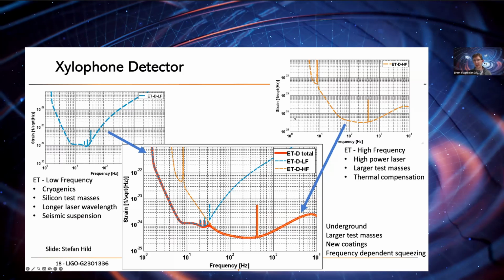Then at the same time, we have a second interferometer, the high frequency interferometer, which uses high laser power, has much larger test masses, and requires, of course, thermal compensation. However, to merge those 2 frequencies, we basically can just use the outputs and post-process, joining the sensitivity curves. Then we get this red curve trace in the center, and hence we construct a wide band sensitivity. So one interferometer operates 2 detectors, and then you have actually 6 interferometers in total, generating 3 full wideband detectors.